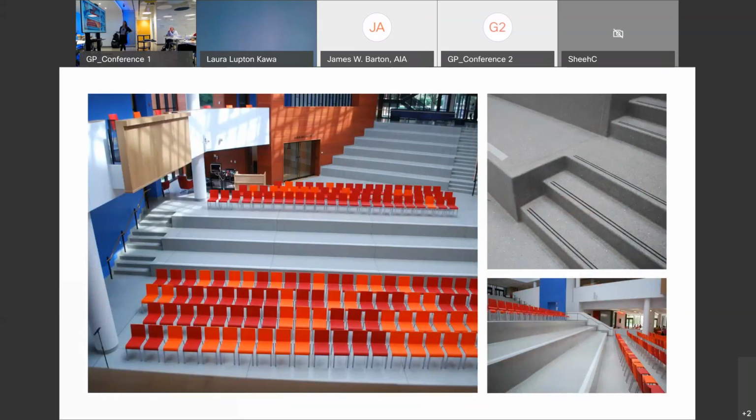What I love about this project is everything you see here is poured, ground, and polished in place. We have the ability to cast terrazzo on a vertical surface. So you can pour right up and over a plinth or these sit style stairs, no issues. There are various different grinding media to do the inside-outside corners, so you have some options available to you. It is installed at 3/8 of an inch, so we don't need to change the thickness at all. This is a nice benefit to the material when you're looking for that poured seamless effect.